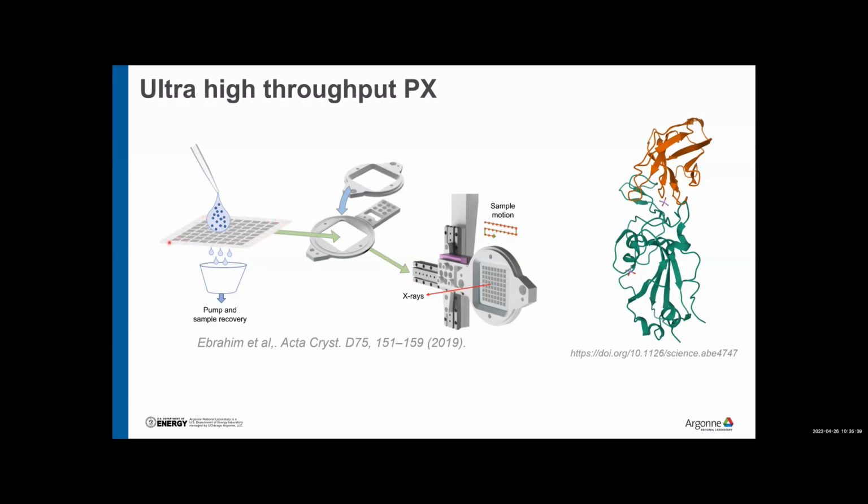This plate has been lithographically etched so that it contains very narrow funnels where these nanocrystals are being trapped. Typically a plate like that can trap about 25,000 crystals. This plate is then put in the beam and you raster scan the plate until you hit these funnels and you hit a crystal.